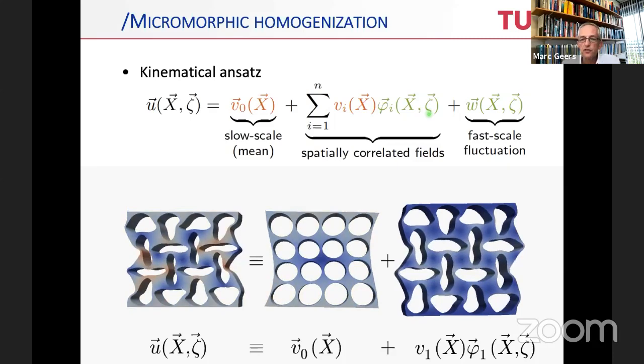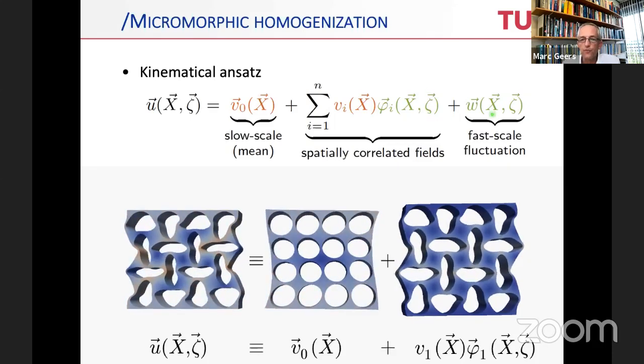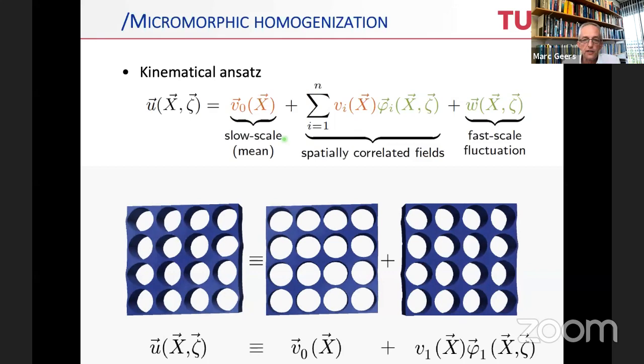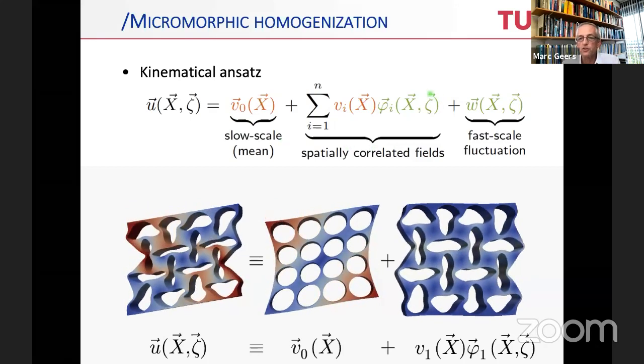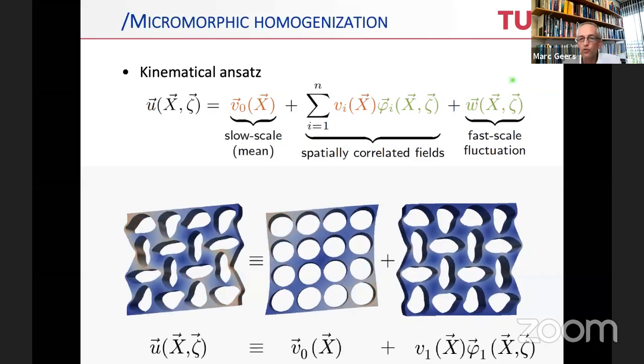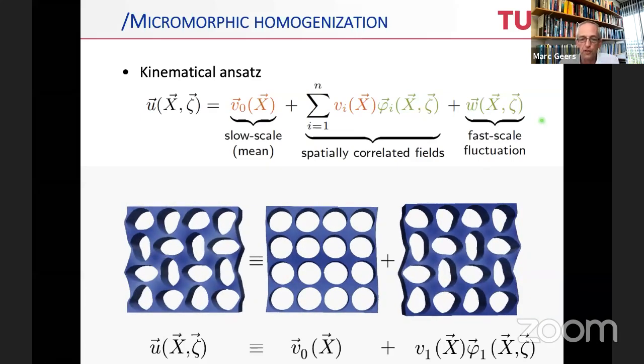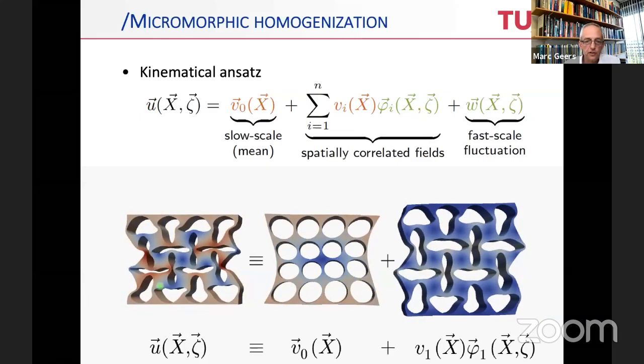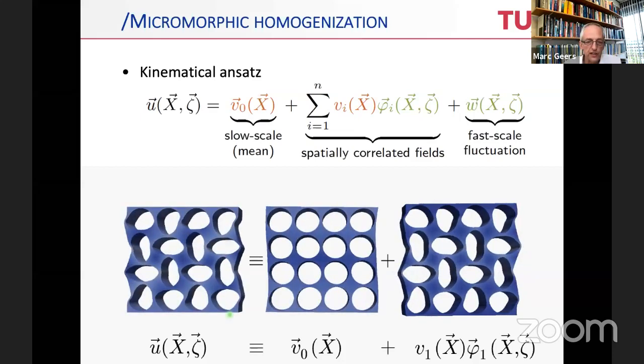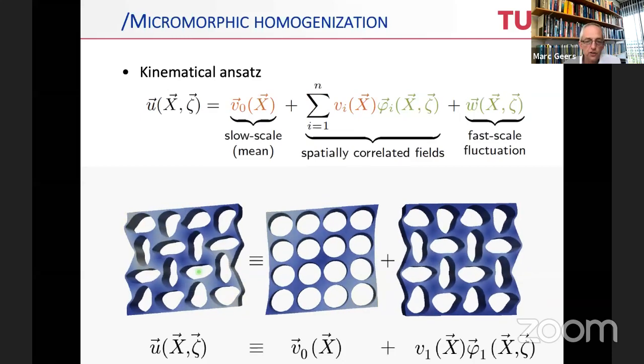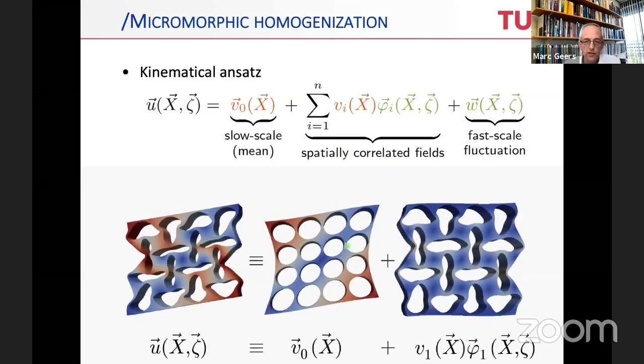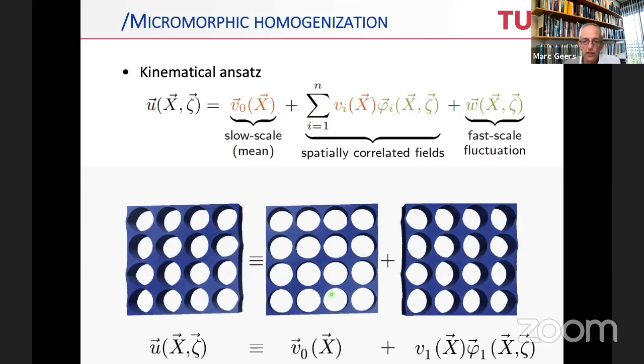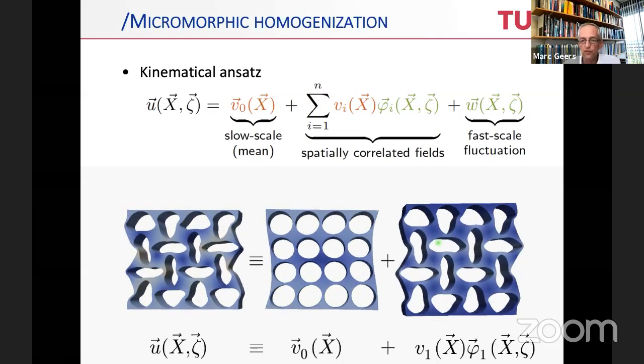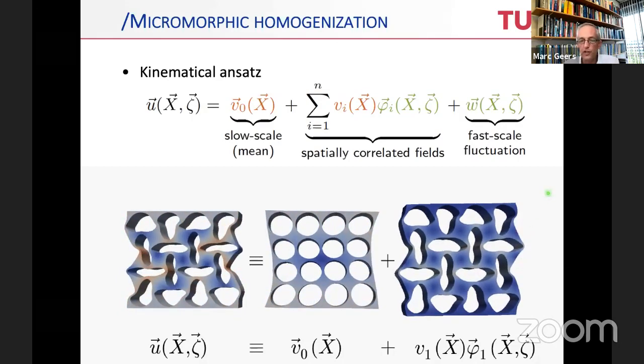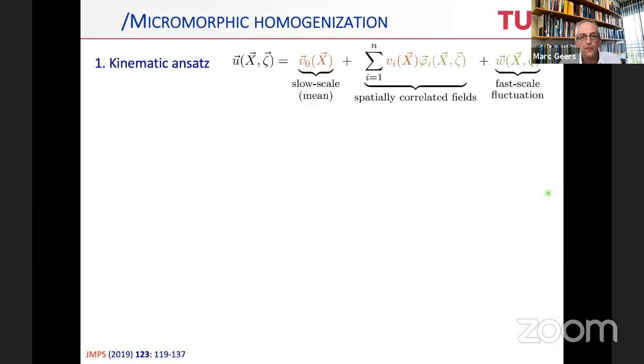For now, this still depends on the position zeta of the microstructure. And whatever is not captured in these two contributions of a typical standard method is the remaining microfluctuation field, which is the unresolved part. So here you see it in a picture. This is the displacement field, which has its mean field contribution, shown here, and then the contribution of the different modes. That's the decomposition that we're adopting here in the micromorphic scheme. So this is the kinematical ansatz, that's step one.